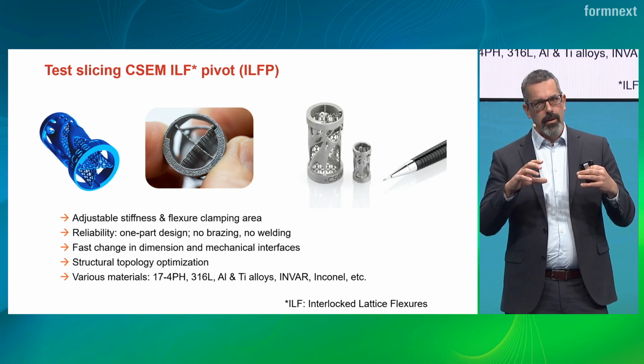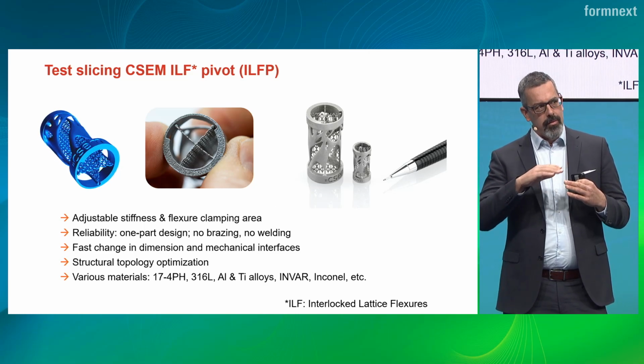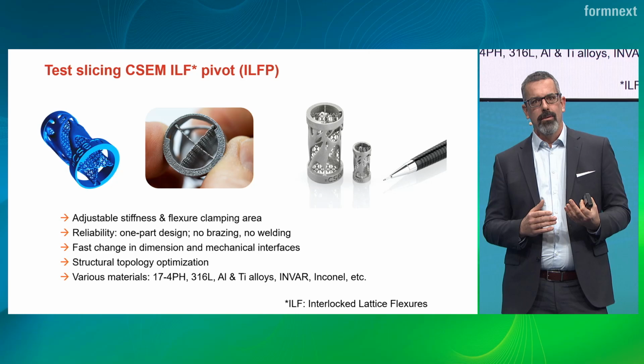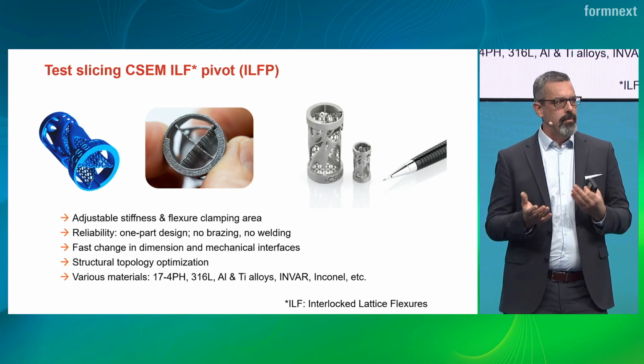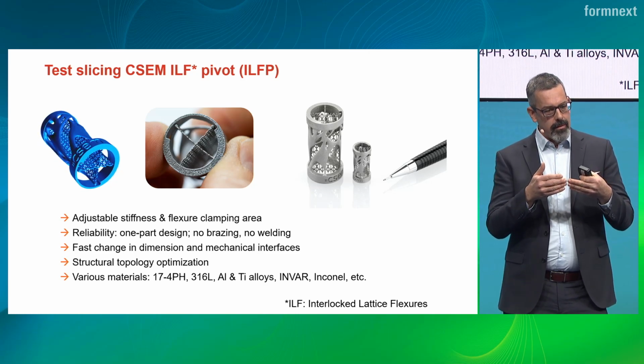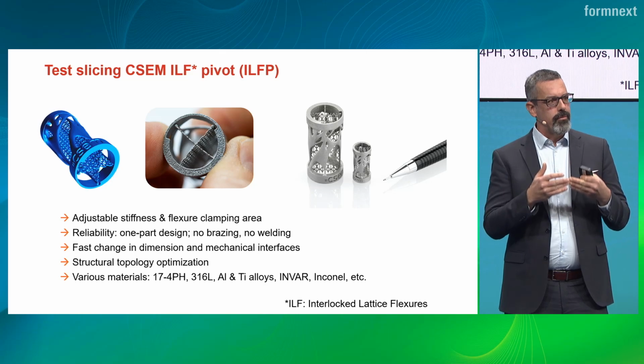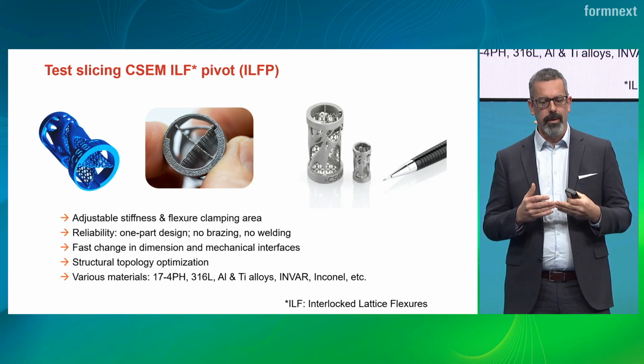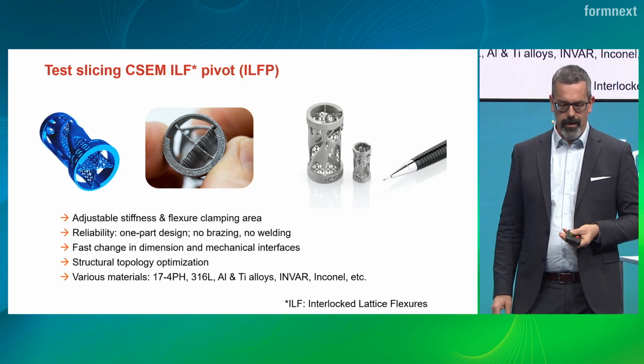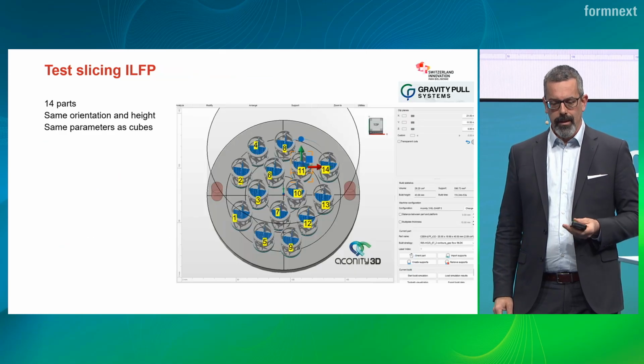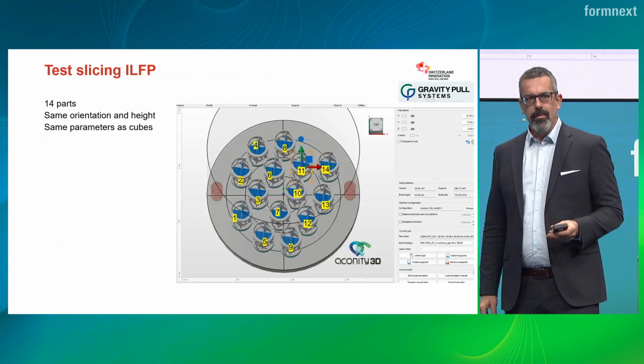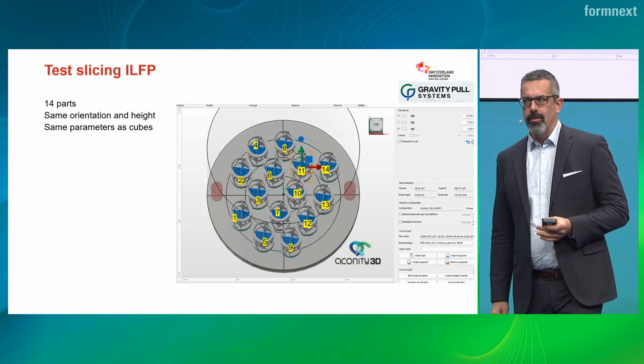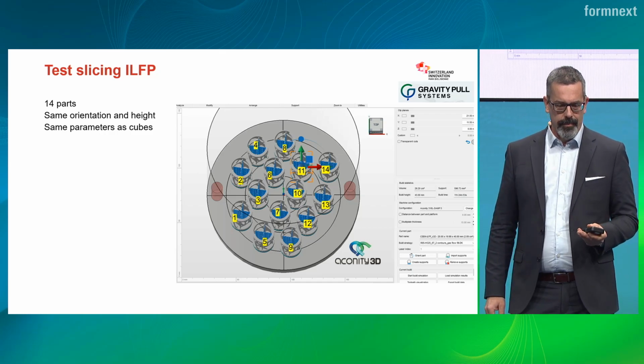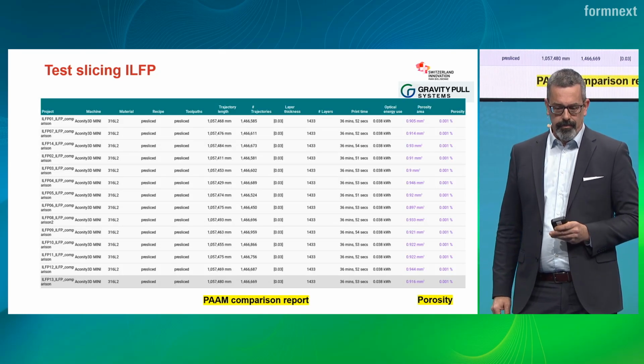And here you see a stable frame and these flexure elements that are highly critical for fatigue, for porosities that are included in the blades. Here you want the full performance that you expect. And there it's really critical what you get and that you know what you get. We place 14 of these pivot mechanisms on the platform, and we analyze them.